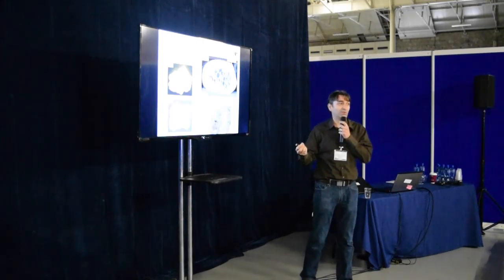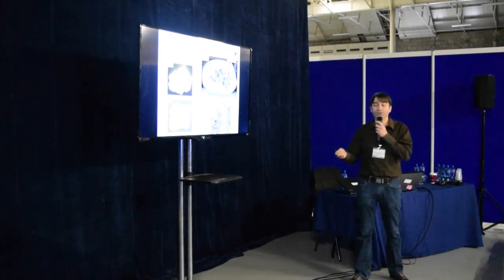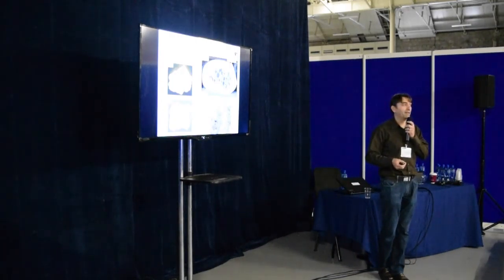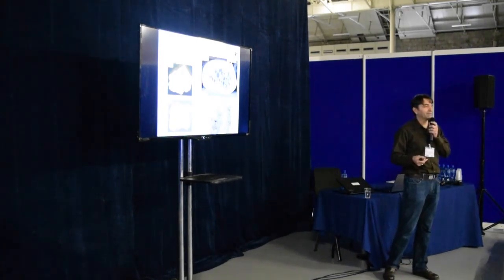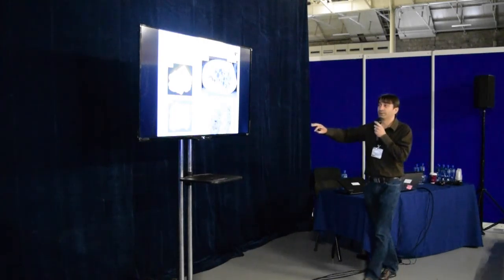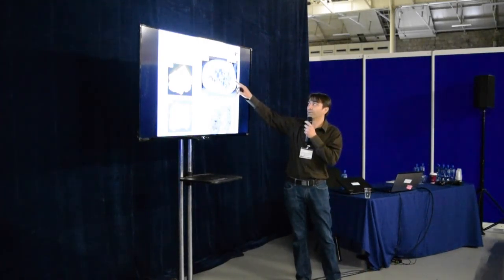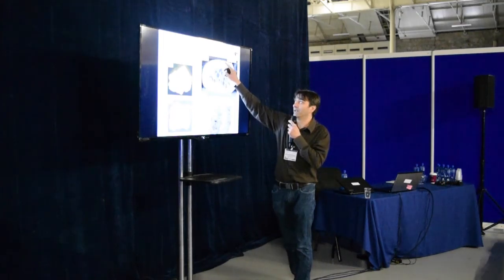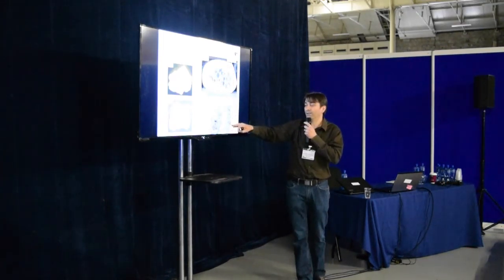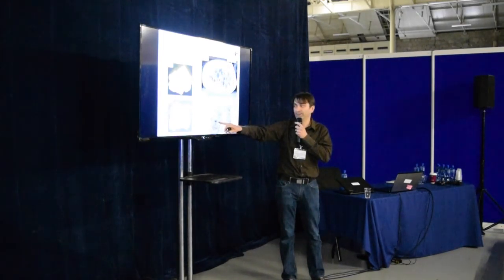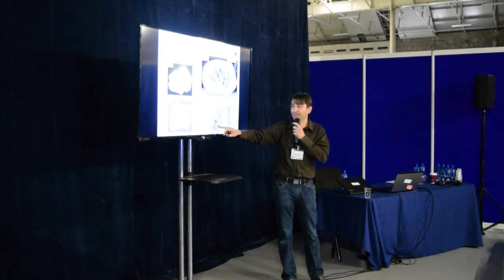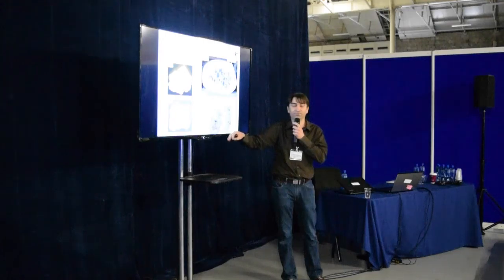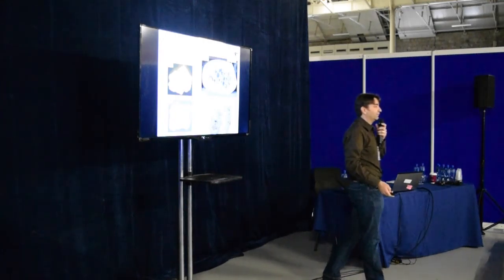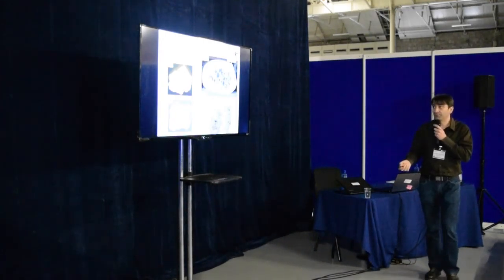It's porous, absorbs the liquid, so we saturate it with the rejuvenator, and then we apply a coating, epoxy coating. And then we have something like this, we have a core here and a shell around it. And then when we break it, we can see that there is an aggregate in the asphalt material full of rejuvenator. When this breaks, it will release the rejuvenator and repair the damage.